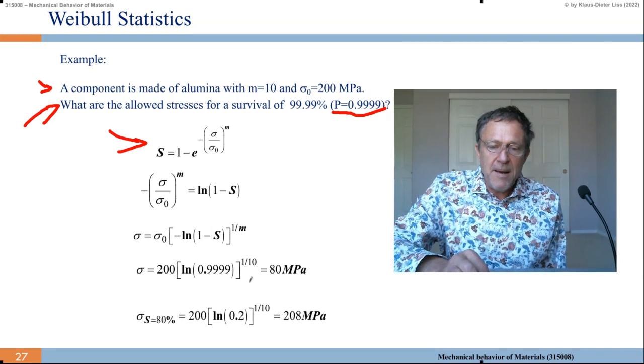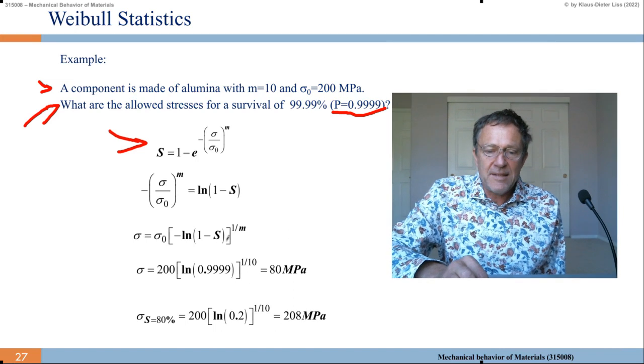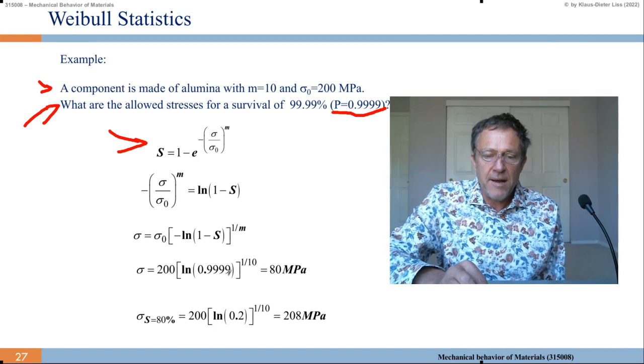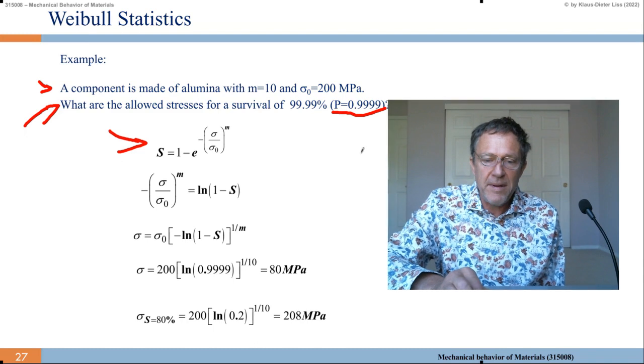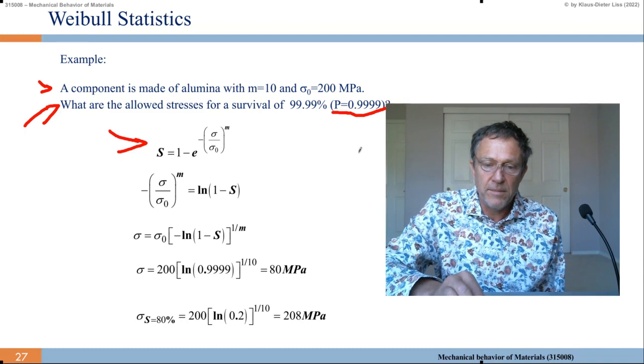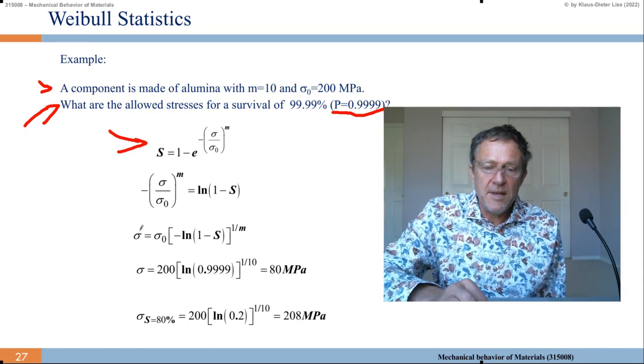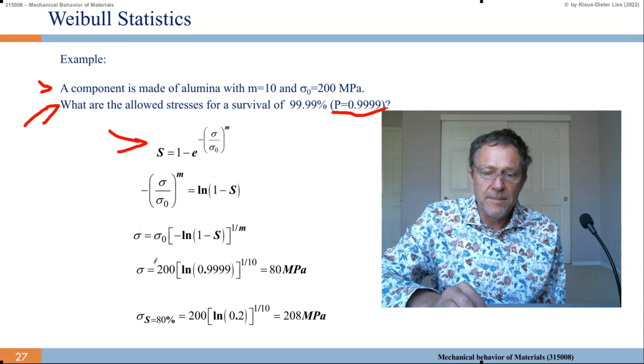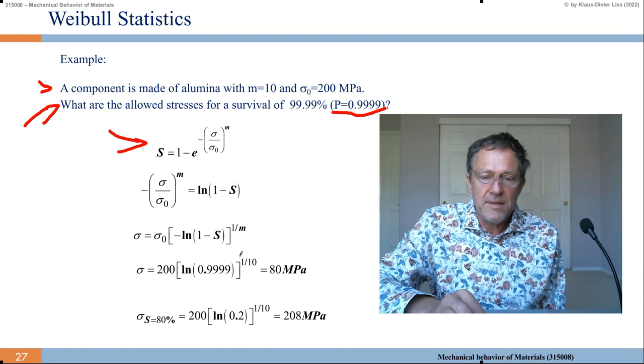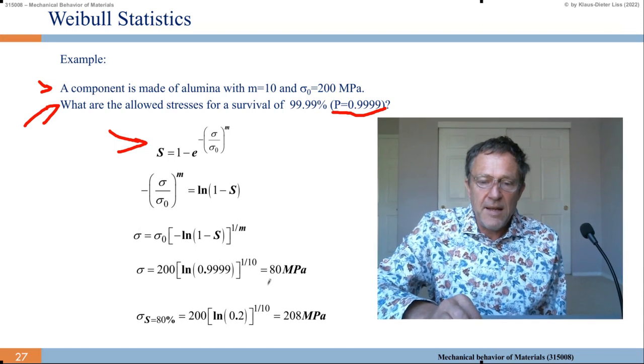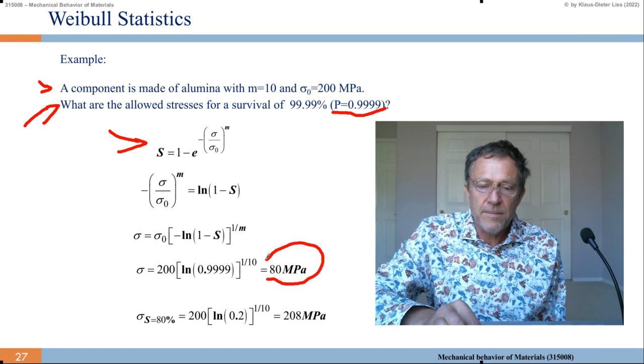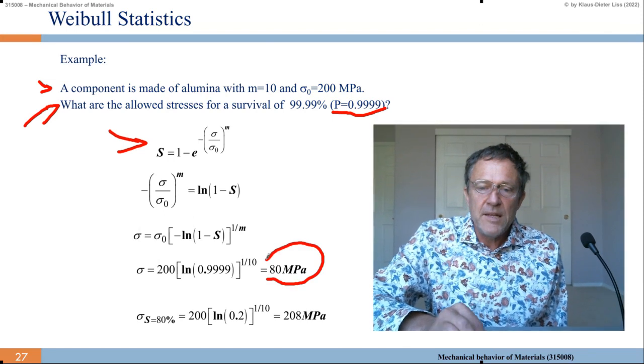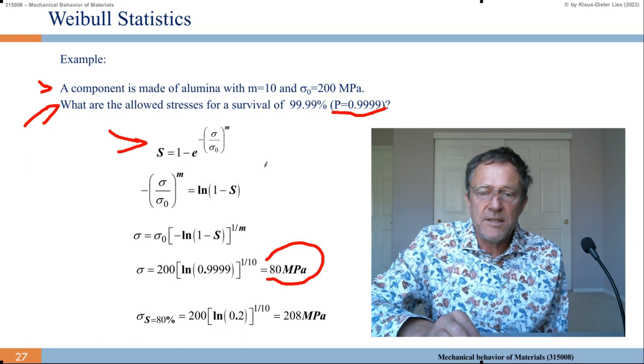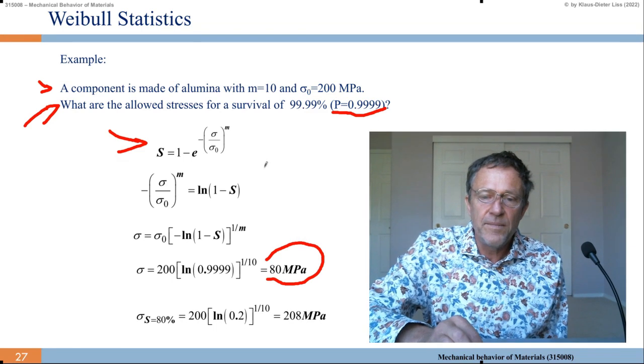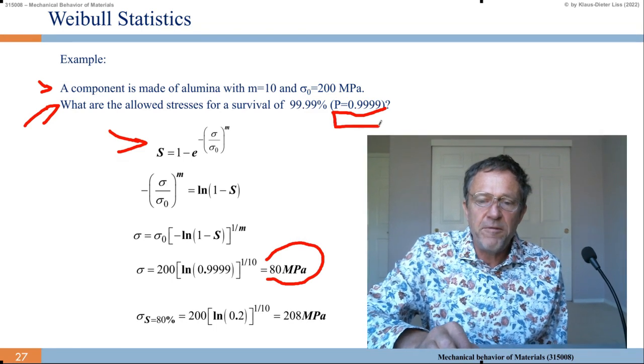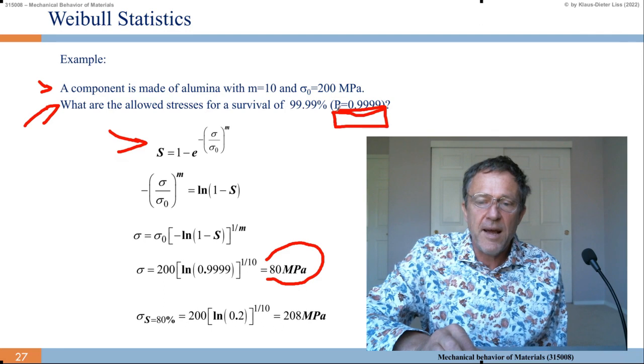And now we put the numbers in. So 1 minus s is 0.9999. This is the probability we want to have. The sigma 0 is 200 megapascal, and m is 10, so 1 over 10. That gives you 80 megapascal. So if I apply a stress of 80 megapascal, then the probability of survival is 0.9999.